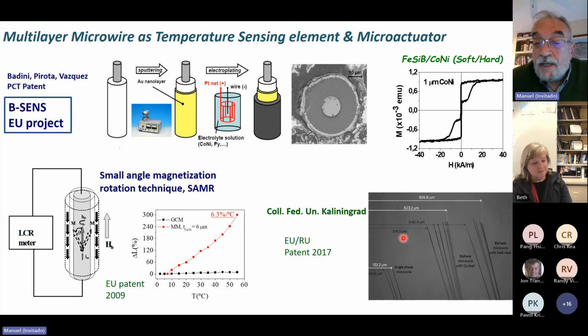Also, more recently, we have been able to prepare another patent making use of these bimagnetic phase microwires that are used as microactuators. These microwires have an intrinsic curvature, which is produced during the fabrication. You may remember that we use this cylinder picking up the microwire. So when we take a piece of this microwire, which has some curvature, and when we apply the magnetic field in one direction, the wire tries to align with the direction of the applied field. So it can be interesting for some particular applications, as I mentioned, as a microactuator.